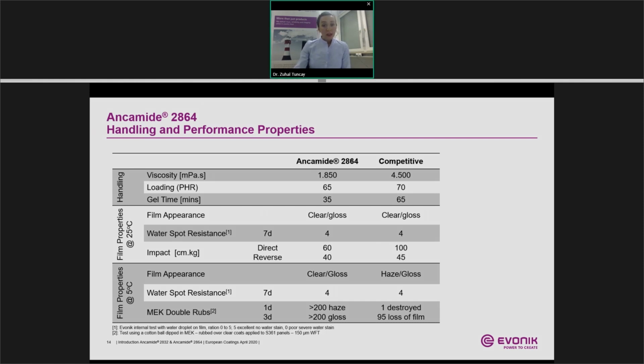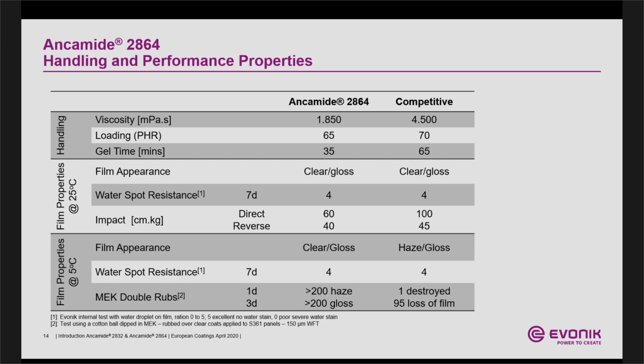Here, where we see real benefit with 2864 is at lower application temperatures. At 5 degrees, compared to the competitive curing agent, we see significant improvement in appearance, where 2864 exhibits high gloss and a blush-free surface. The water spot resistance is comparable. And when we examine the film for coating integrity using the MEK double rub test, there is a significant difference in performance.